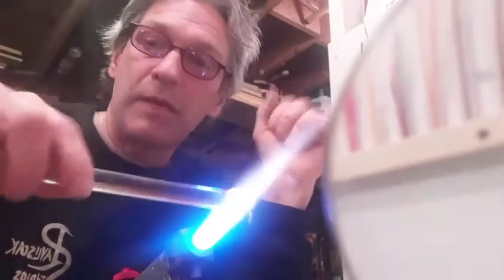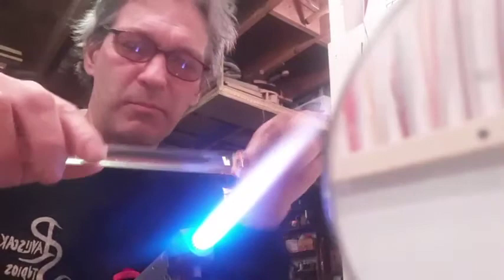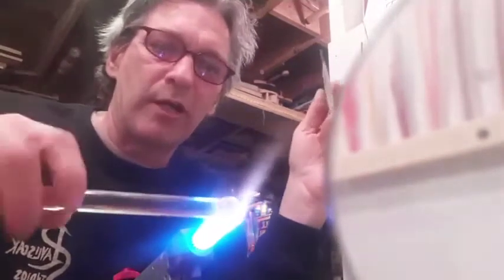Alright, I got a crack in my rod, and as I continued to enlarge my gather, that crack remelted and became some bubbles, and I was just tweezing those off. That's what that hiss was, me grabbing the bubbles out with my tweezers and quenching them in the fire.